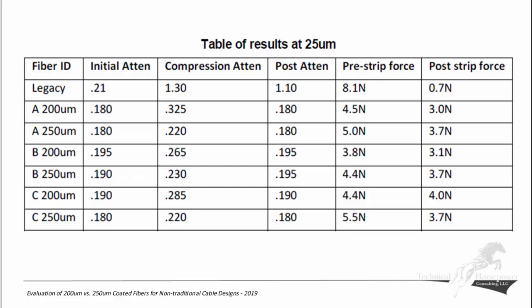Now, as we go down from fiber suppliers A, B, and C, you'll see that the values were pretty consistent. The 250 micron had slightly less loss than the 200 micron, but not a significant difference. And post-attenuation, they all pretty much return to their pre-attenuation, post-compression. The attenuation stayed pretty much where we want it to be.